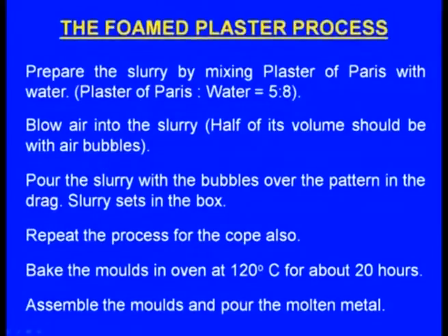Now here the modification comes into the picture. Blow air into the slurry, half of its volume should be air bubbles. So once the slurry is made, we will be blowing air into the slurry, so that there will be so many bubbles. Half of the slurry is filled with bubbles.